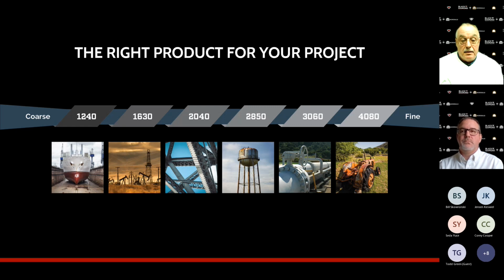The proviso is that you have enough aggressiveness in that abrasive to remove the coating or rust that's on there. So if we get into a situation where we've got heavy epoxy or a lot of rust, then the 3060 is not going to work as well because it just doesn't have enough momentum, doesn't have enough kinetic energy, being the smaller particle size. So you've got to move up in size, and in doing so, you're going to impart more energy on each particle to the substrate to remove that epoxy, to remove that rust.